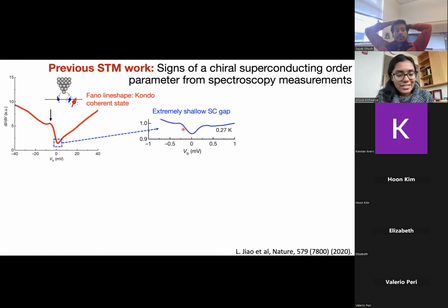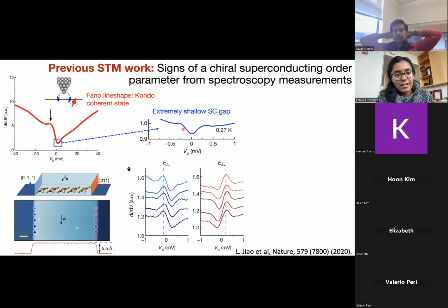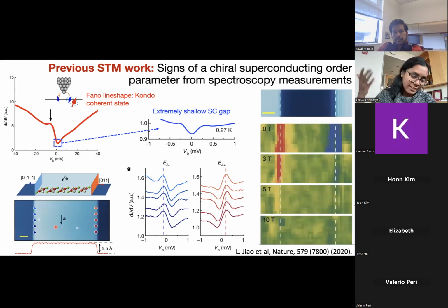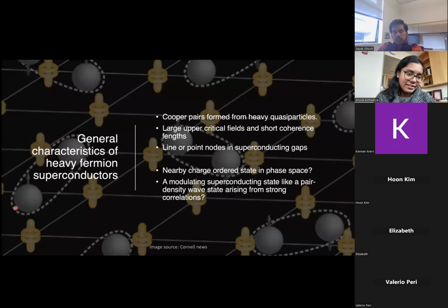However, the interesting observation is when you go to step edges in this material, you see a state inside the superconducting gap that seems to know what step you're actually measuring the spectra on. It has this strange particle-hole asymmetric shape on opposite step edges. I don't think there's a clear understanding of why the shape is this way, but all we know is that this is tied to the superconducting state, because as you increase magnetic field and go to around HC2, it becomes undetectable.